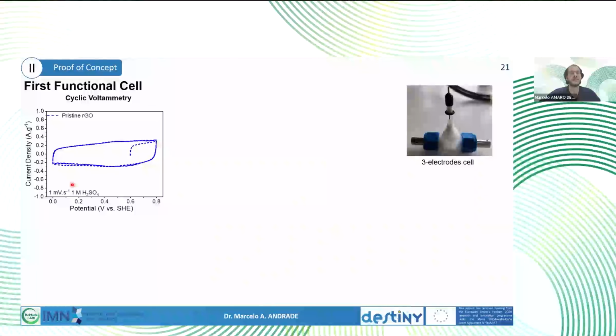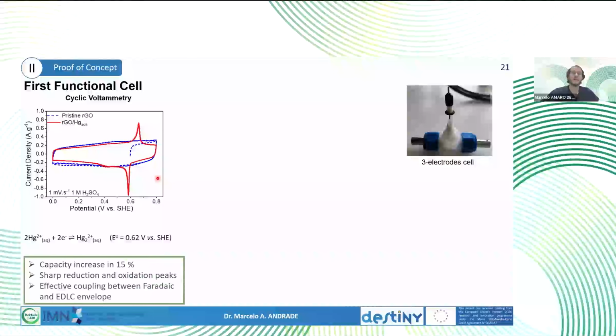So here you can see the cyclic voltammogram of the pristine RGO. So that's a typical EDLC envelope. So you have only double layer capacitance coming from the graphene. But once they're loaded with the mercury, there are beautiful redox peaks at around 0.62 volts versus SHE, which corresponds to this mercury redox reaction, and a capacity increase of 15% relative to pristine RGO.